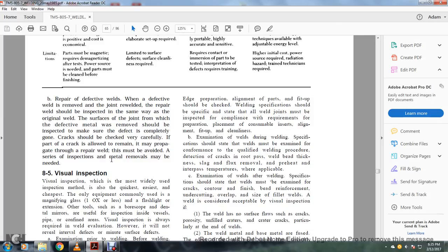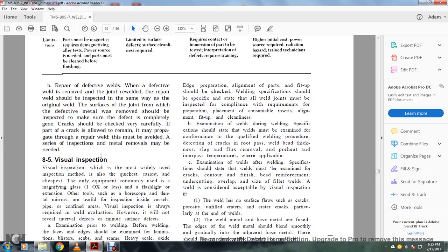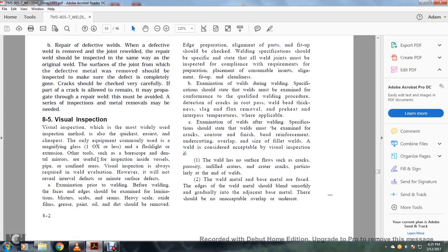When the defective weld is removed and the joint re-welded, the repair shall be inspected in the same way as the original weld, but the surface of the joint from which the defective metal was removed should be inspected to make sure the defect is completely gone, and the crack should be checked very carefully. If part of the crack is allowed to remain, it may propagate through a repair weld. This must be avoided. A series of inspections and metal removals may be needed.